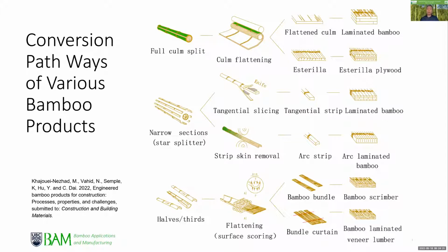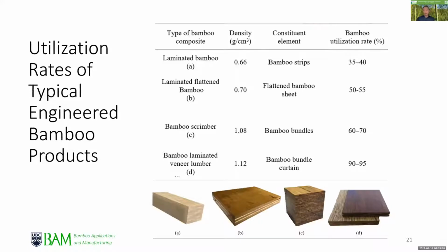On the other hand, there has traditionally been work done to produce esterilla, and that can also be made into a panel product. And if you look at even the way bamboo scrimber is produced, you can process the bundle and randomly place them and then press them, or you can line them up into a curtain and then press them, more similar to the way the laminated product is produced. So in those different process pathways, that would create a different product and different densification, because the need to create the intimate bond and the structure of the elements and how they are prepared, the densification will be different.